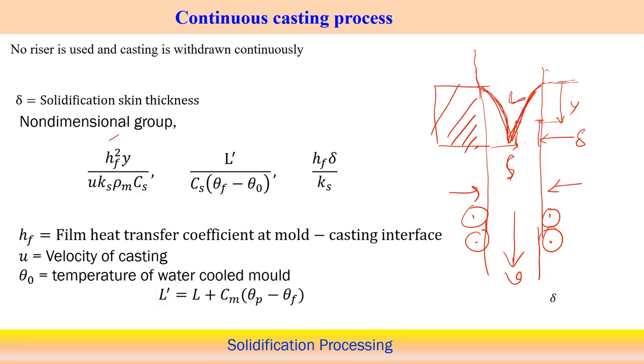And we see that at a distance y, delta is the solidification skin thickness, and we usually analyze this to understand the different parameters using non-dimensional groups. I'm not discussing how these non-dimensional groups are formed, but just to know that there are several non-dimensional groups for the different parameters. Here we can see hf, the film heat transfer coefficient, into y. y is a variable distance. So at a distance y, we define the skin depth, the solidification skin thickness delta.